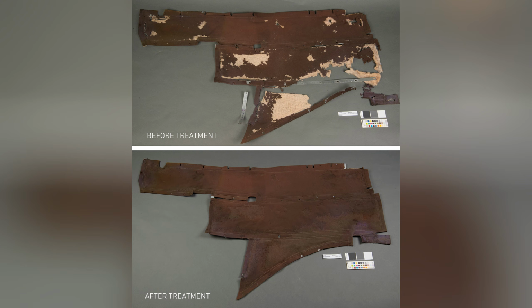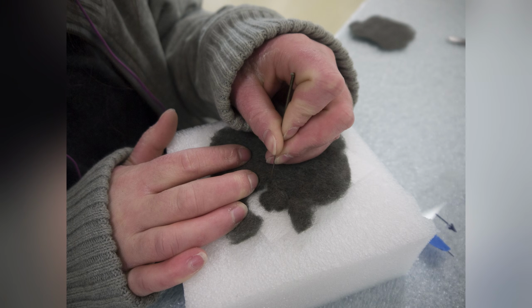Here, the trade-off moves in the opposite direction: retain as much World War II material as possible and adapt textile conservation methods to secure the bomber interior. The treatment does not depend on replacing the panels wholesale. Conservators develop 3 stabilization paths. Larger losses can receive laser-cut fabric fills shaped to the original voids. Smaller losses can be integrated with needle-felted wool fibers. Where the original textile is too fragile to carry itself, a lining support can hold the remaining traces in place. The new material is made visually subordinate to the original fabric, so the repair stabilizes the panel without pretending the damage never happened.